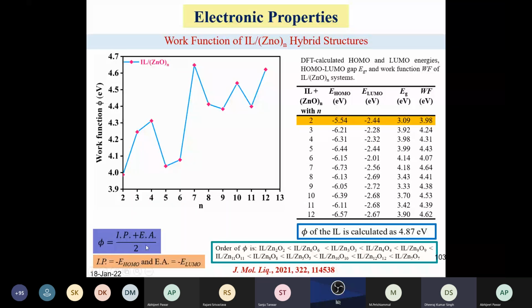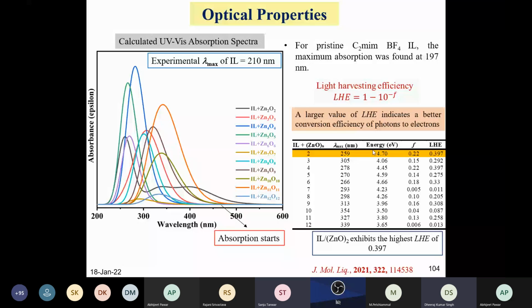So you can find out this value, and you can calculate the light harvesting efficiency of these clusters, ionic liquid and zinc oxide nanoparticle cluster, which is 1 minus 10 to the power minus f, where f is the oscillator strength, the absorption intensity of your particular nano cluster. Using this simple equation, you can calculate the light harvesting efficiency of various nano clusters with ionic liquid. And we found that with two types of zinc nano cluster, it shows the largest light harvesting efficiency, 0.39. Due to this, we have applied these various zinc oxide nanoparticle clusters in solar energy applications.